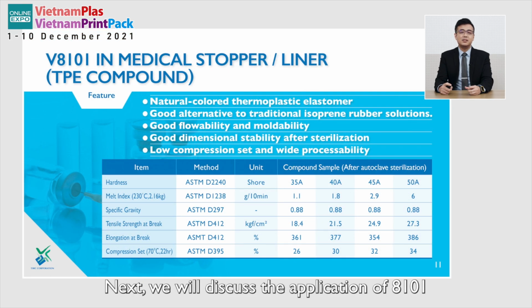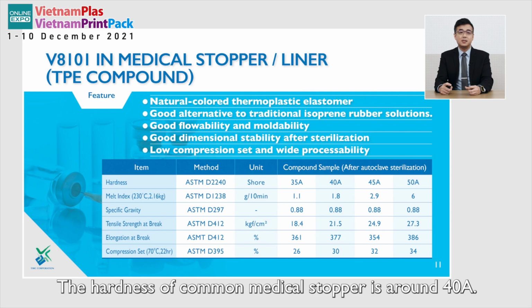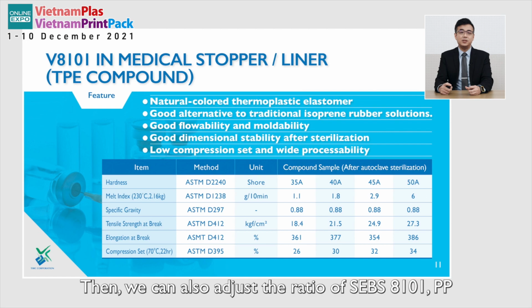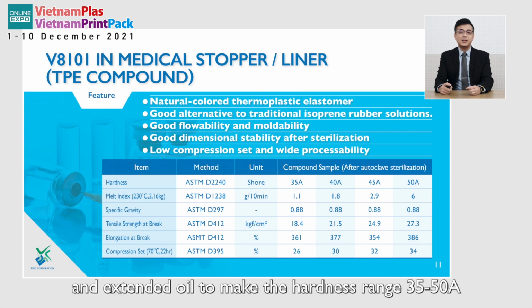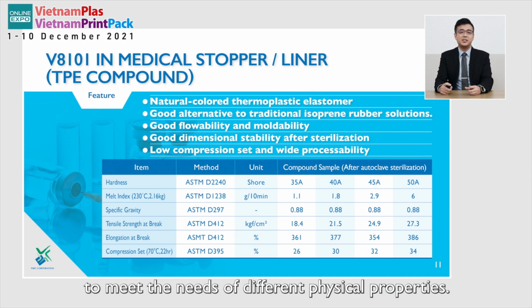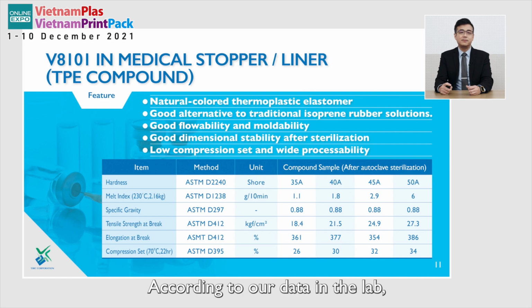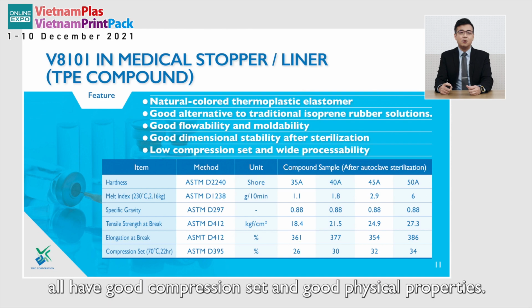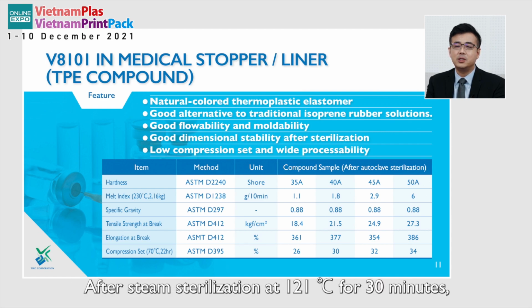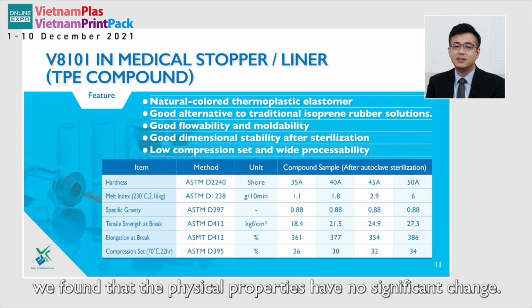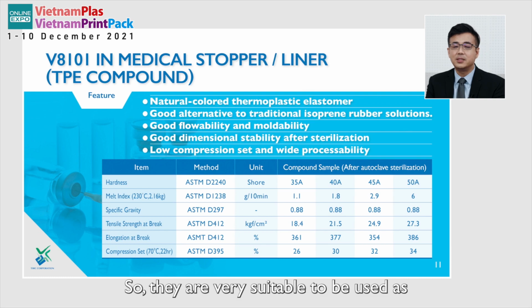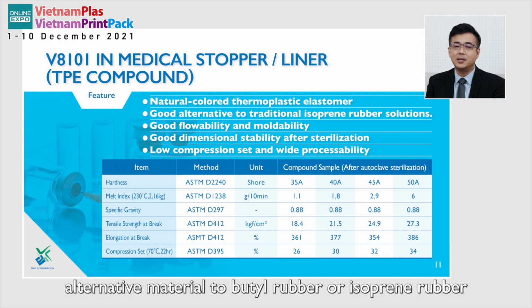Next, we will discuss the application of 8101 in medical stopper and liner. The hardness of common medical stopper is around 40A. Then we can also adjust the ratio of SEBS 8101, PP, and the extended oil to make the hardness range from 35 to 50A to meet the needs of different physical properties. According to our data in the lab, these four formulations of different hardness all have good compression set and good physical properties. After steam sterilization at 121 centigrade for 30 minutes, we found that the physical properties have no significant change. So they are very suitable to be used as alternative material to butyl rubber or isoprene rubber.